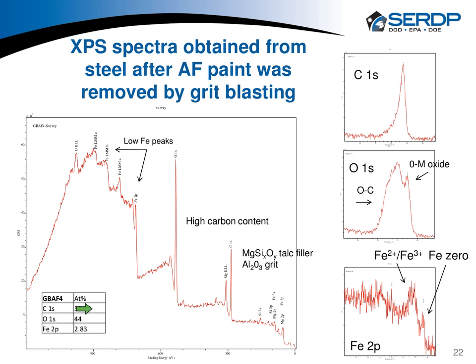And notice here that there still was a fairly high concentration of carbon on the surface and a fairly low concentration of iron. Now, I don't know if this particular sample was pretty typical of a grit blasted sample. And notice in the oxygen region that the contribution due to organic, or shall I say oxygen bonded to carbon, is fairly high, or at least equal to the ratio of oxygen bonded to the metal. When looking at the iron spectrum, there's a combination of peaks from ionized iron, iron plus 2, iron plus 3, and also, interestingly, a peak due to iron 0. Well, this goes back to what I was saying earlier about the effect of grit blasting a surface, going all the way down to metallic iron and then subsequently an oxide growing.